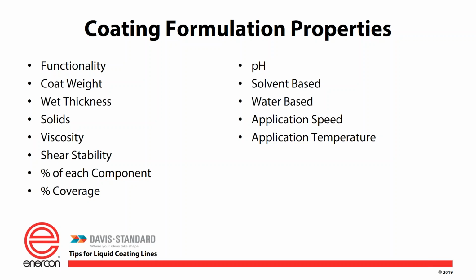Right. Then is your coating formulation solvent-based or a water-based formulation. Solvent-based requires that we handle the exhaust leaving the dryers. Normally, it's either going to be in a recuperative mode where we're going to try to put it through a carbon bed and get your solvents back out and reuse them, or it's going to go into an oxidizer, which heats up to very high temperatures and destroys the solvent so it doesn't go into your atmosphere. Solvent-based also requires a design on the machinery to be made so it's explosion-proof, flame-proof. So we'd either put enclosures around those areas that are wet, or we would design special electronics where it's air purged or sealed off.